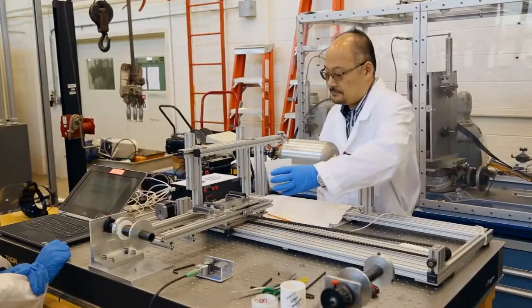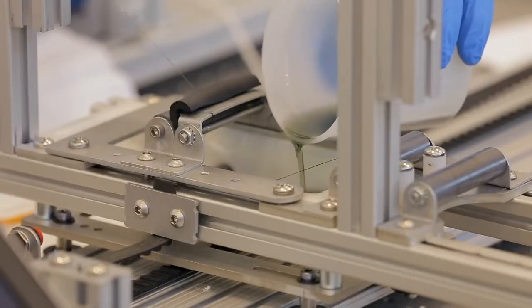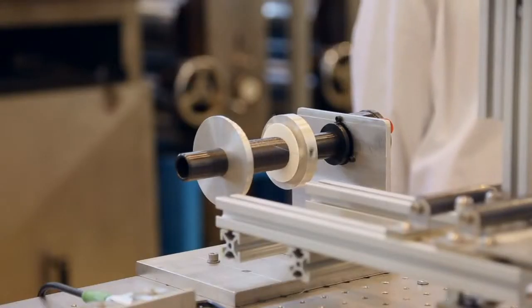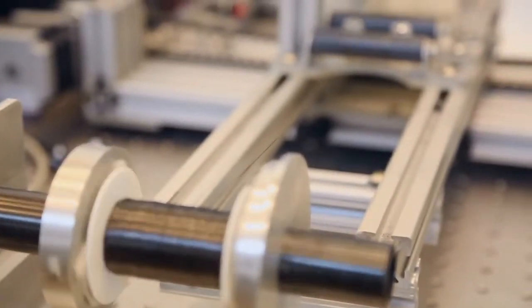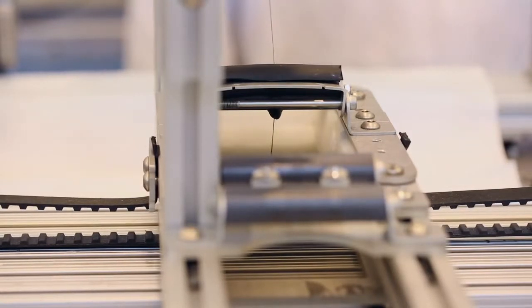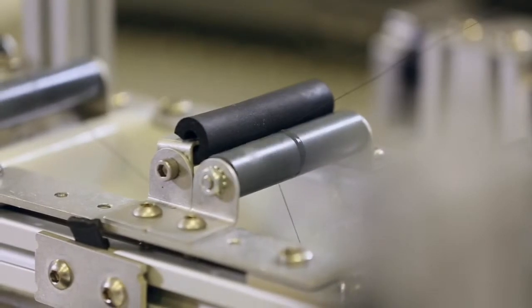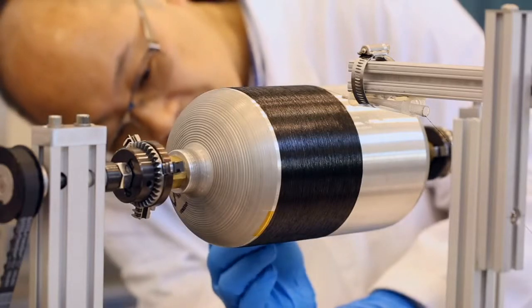What are the benefits of miniaturizing the entire process? So several benefits come out of that. One is we basically are tailoring the process that we're developing to the amount of material that's available. We can very quickly rapid prototype in a sense. We can try several different conditions very quickly, changing that using the least amount of material. And also it allows us to modify the machine very quickly to adapt to what we learn as we are winding this material. When you miniaturize it, are you skipping steps? Because when you look at your device, you don't have many moving parts compared to the commercial size. That's correct. And so what have you done to get the same benefits? Okay, so here are the critical steps. You take the yarn, which is dry, and then we need to send it to a bath so that the resin will be absorbed onto the yarn. And then after the resin is absorbed, really what we want to use that infused yarn with is to wind it around the bottle. Okay, so in a very short distance, we're able to achieve that. It's in about a couple of feet. We're able to see that process right away.